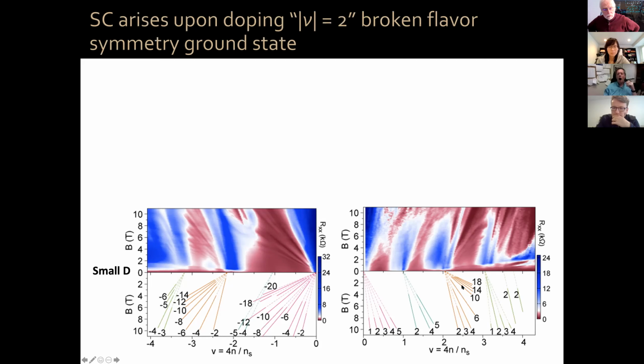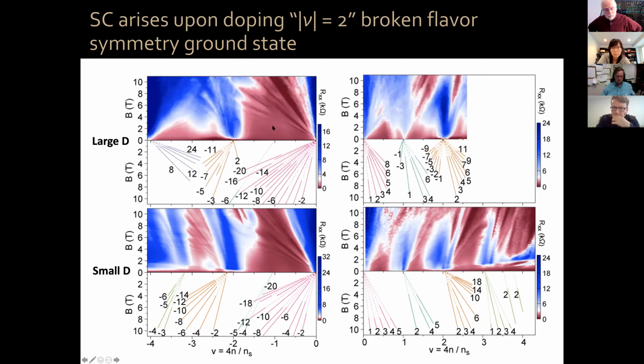Okay, now the degeneracy of your Landau levels tells you how many Fermi surfaces you have. So it's 2 in particular after nu equals 2. Okay, it's 1 after nu equals 3. That again tells you how many empty flavors you have. Okay, now if you go to large displacement field, what we noticed is that we start to see Landau fan diagrams also pointing inwards towards charge neutrality. Okay, that tells you the following. In particular, the most interesting is what happens around nu equals 2.